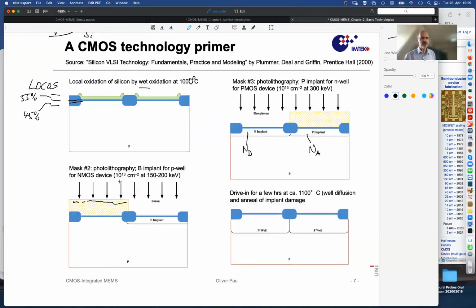So what do these numbers mean? 10 to the 13 per square centimeters. That's the number of boron atoms that are deposited per area. And they don't stick there on the surface. They go inside, so they distribute over a thickness. But that thickness is experimentally well known by the knowledge of the implantation process. When you shoot at a surface with 150 kilo electron volt boron atoms, you know that they go so and so deep on average, and will establish some profile, and you have that under control. But how many of those are there at this depth or distributed around that depth is given by this number, 10 to the 13 per square centimeters.